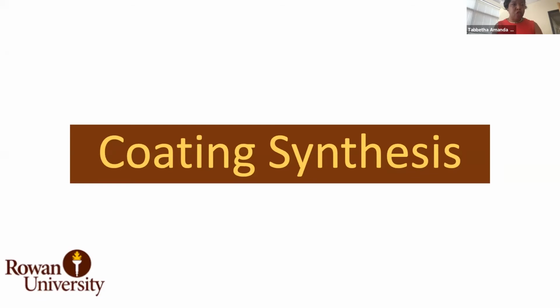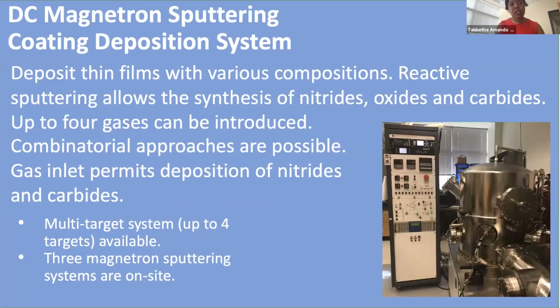And then finally, within the suite of instruments that I'll cover, we have coating synthesis instruments, and we have 4 such instruments that are DC magnetron sputtering coating systems. And these systems allow us to actually sputter from multiple targets at the same time to form a thin film coating onto your sample surface. We also can introduce gases into the system at the same time, so that if you need carbide coatings or oxide coatings and so forth, or nitride coatings, we're able to carry out those depositions.